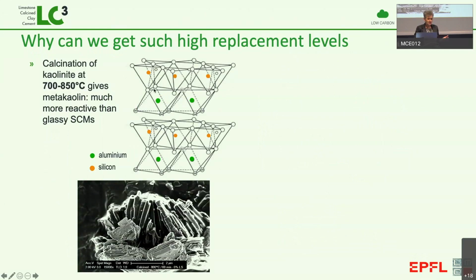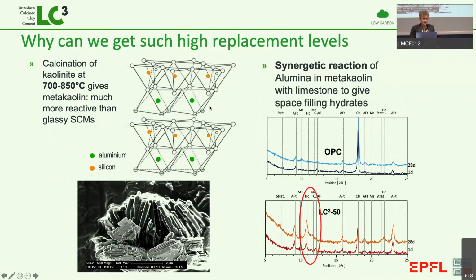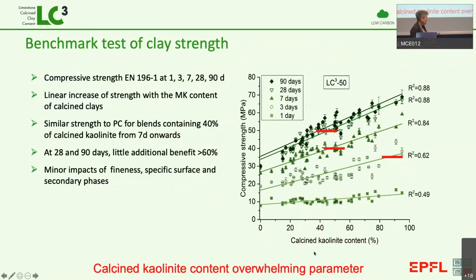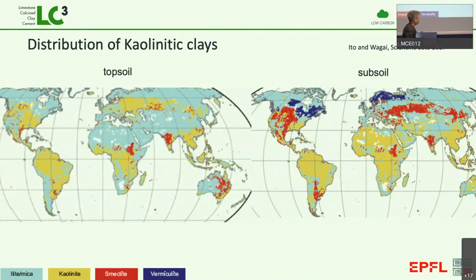You have a layer of silicon and alumina together, and when you heat these up, they become disrupted, and then, in fact, the alumina can react with the limestone to form these compounds here, which fill space and contribute to strength. So we've now tested more than 70 clays from all around the world, and basically we see the performance correlates simply with the amount of kaolin in this structure. Kaolin is one specific clay type, but it's distributed very, very widely around the world.